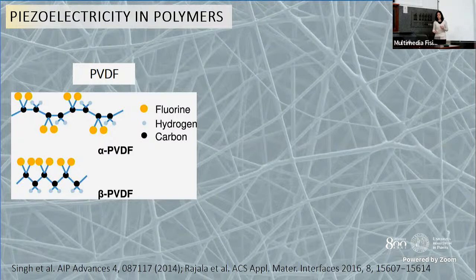And this is because this beta phase is characterized by a distribution of fluorine atoms and hydrogen atoms in this sense. So they're opposite with respect to the carbon backbone. And this, due to the electronegativity difference between these two atoms, enables the formation of a dipole perpendicular to the backbone. And this dipole, of course, enables the formation of a polarization vector and so piezoelectricity in the material. However, as I mentioned before, this is a synthetic polymer, but it is biocompatible, but we can do more.